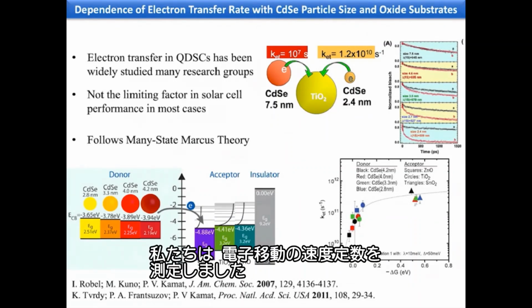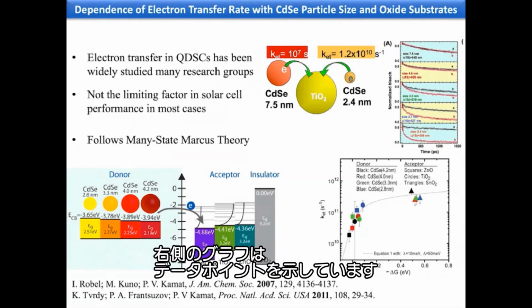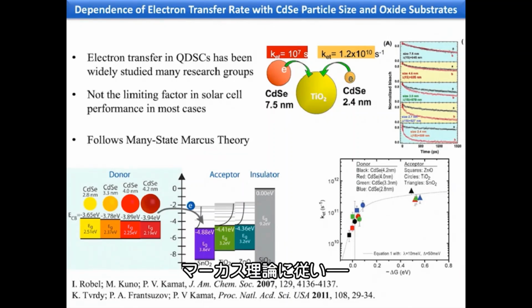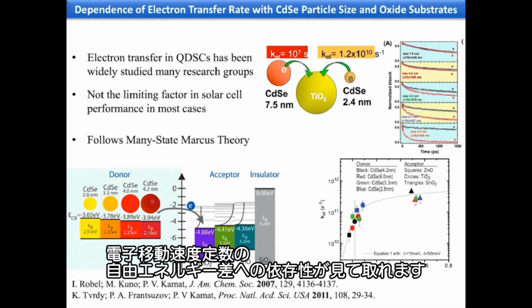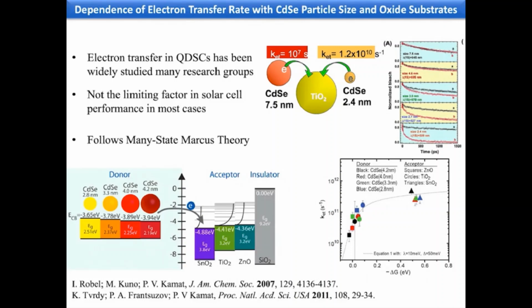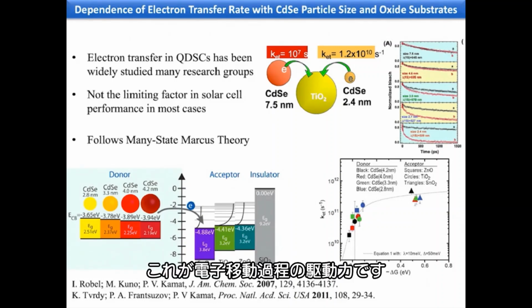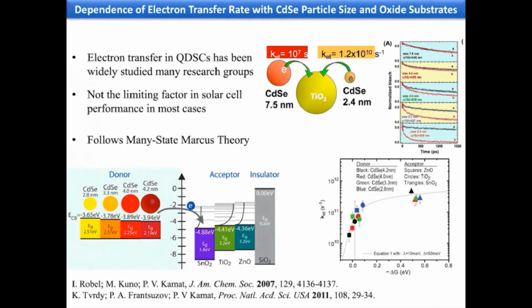So we measured the rate constant for electron transfer, and this right hand panel shows our data points and a fit of many-state Marcus theory, showing the dependence of the electron transfer rate constant on the free energy difference that is driving the electron transfer process.